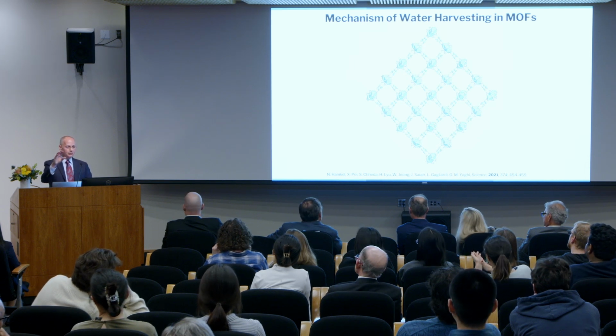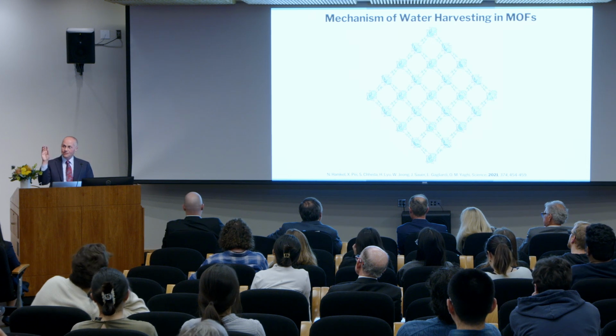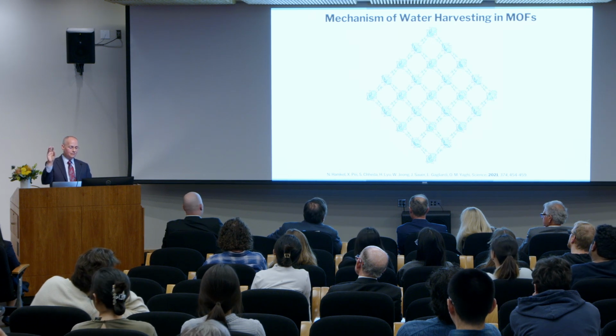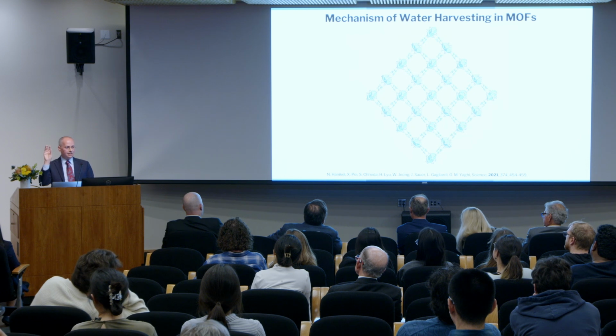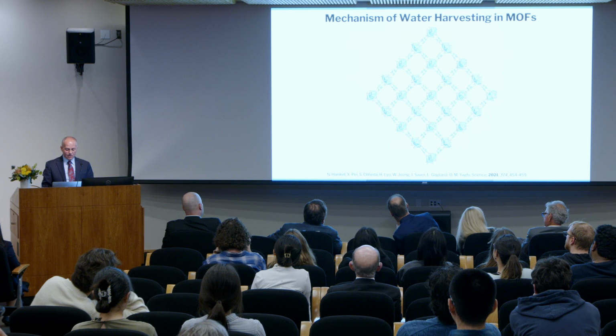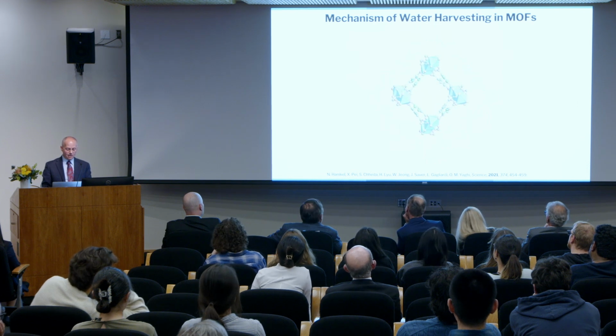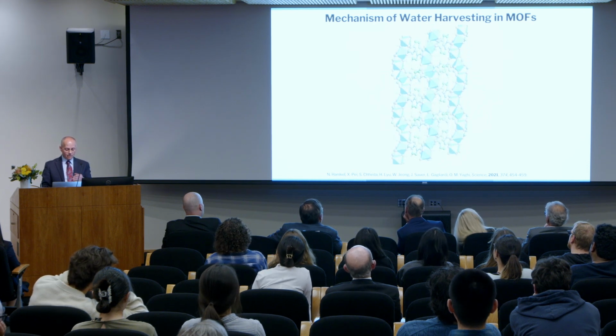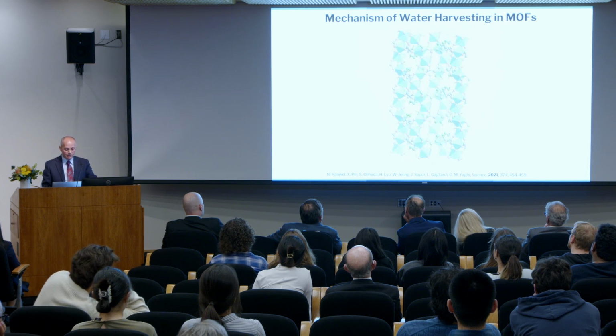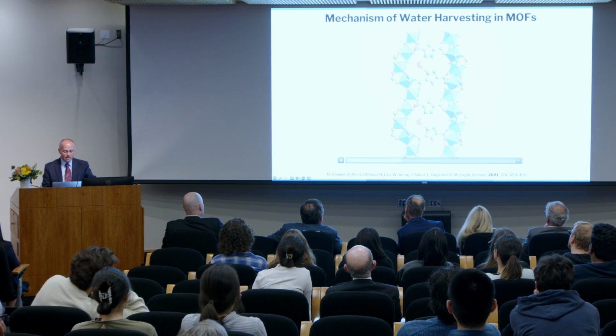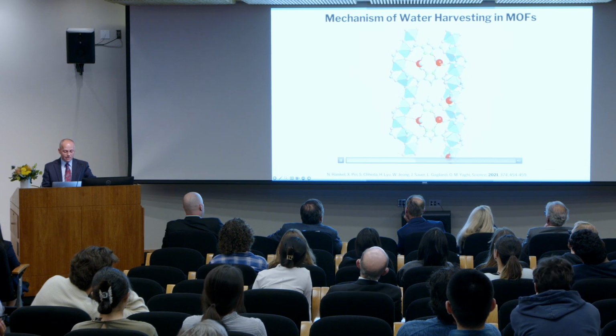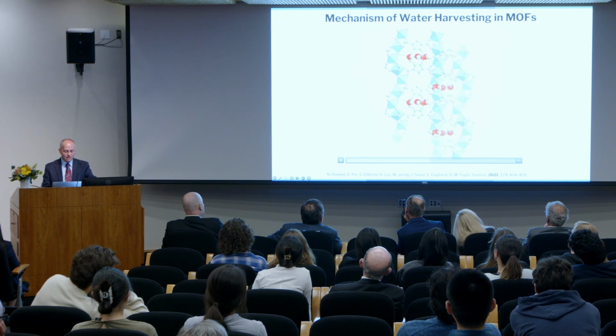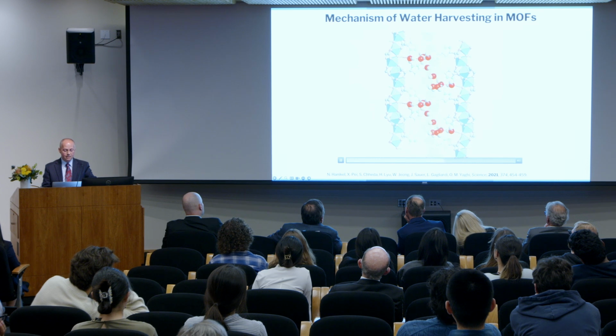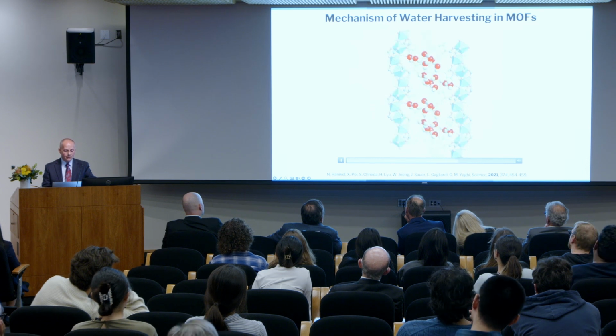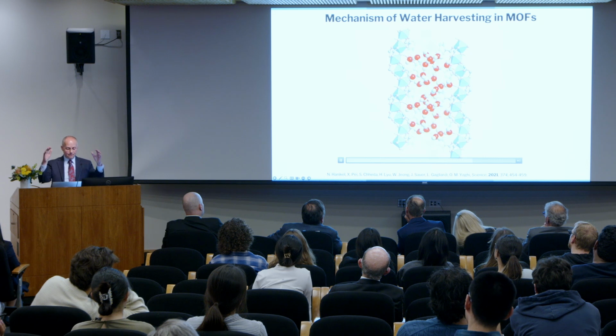If you're a water molecule floating through the pores, you will be viewing hydrophilic and hydrophobic pockets. And they are repeated throughout, billions of them throughout the material. And so I'm going to just extract one of these pores to highlight what happens. I'm going to shave it down to show the hydrophilic sites and the hydrophobic sites. The first water molecules obviously go to the hydrophilic sites, then the hydrophobic sites are bridged through hydrogen bonding. Okay, they repel the water, but hydrogen bonding to the hydrophilic sites fills up the pores.